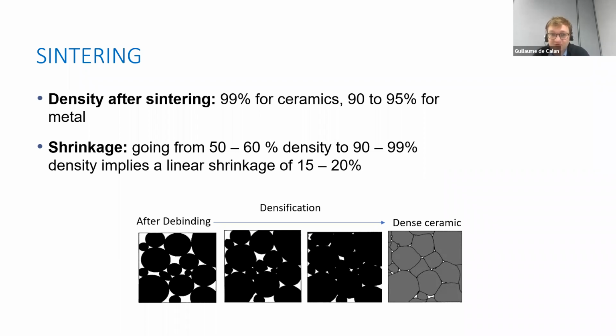We typically go from a part which is after debinding very porous, of course. It has between 40 and 50% of porosity, to a part which is a lot denser, between 90 and 99% density. Ceramics is 99. Metal is usually 95. It does depend a bit on the sintering process, but that's the usual value, which implies the shrinkage we were mentioning, the shrinkage of 15 to 20%, which is very significant and which is quite impressive when you see the part.